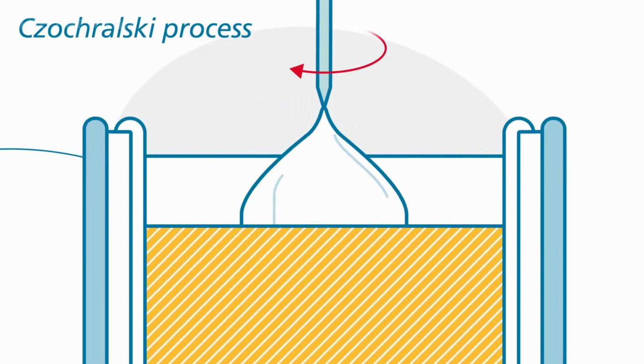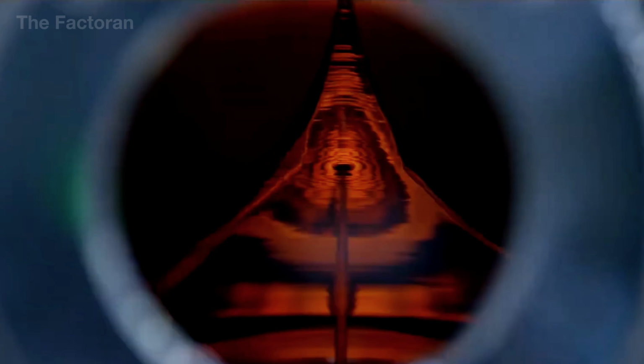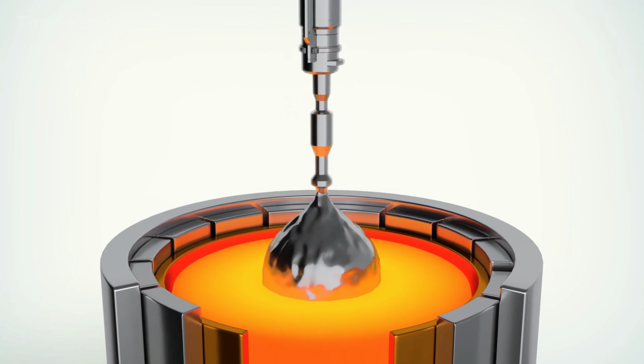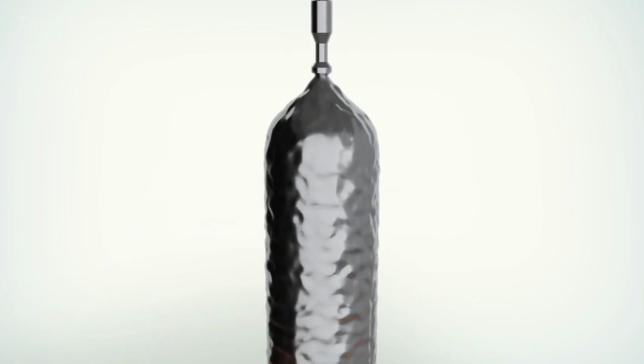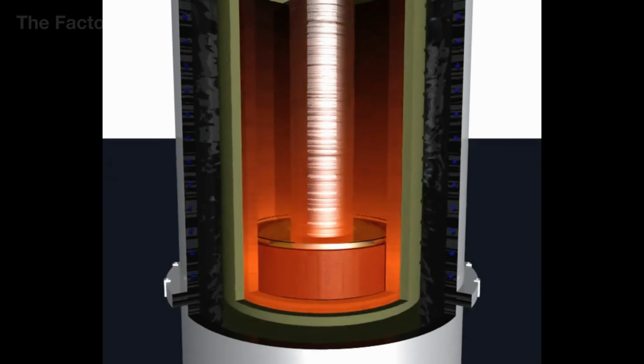At this stage, a single crystal seed is dipped into the surface of the molten silicon and begins to be pulled upward in a vertical direction. The process unfolds extremely slowly, typically just 1 to 3 millimeters per minute, while both the seed crystal and the crucible rotate in opposite directions to stabilize the internal convection flow. The diameter of the crystal is not fixed in advance, but continuously controlled through temperature and pulling speed. Even a slight change in lifting speed or heating power can shift the diameter by a few millimeters, enough to ruin the entire ingot. Sensors monitor the shape of the neck region from the very first centimeters, as this is the critical zone for eliminating initial structural defects.